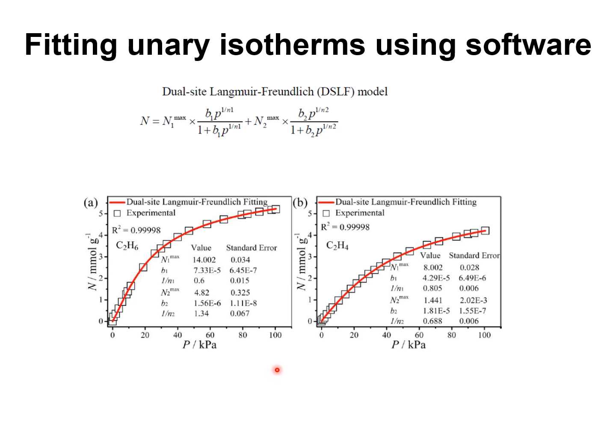any physical significance. Indeed, I've taken this data and fitted it with a single site Langmuir model to an accuracy that is acceptable. So the use of a dual site Langmuir Freundlich model in these two cases is definitely an overkill.